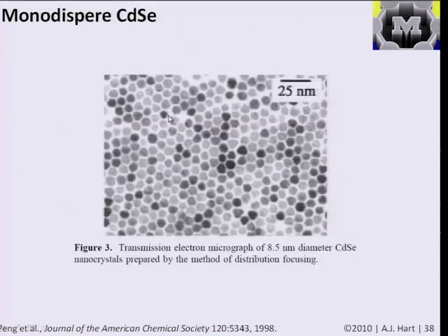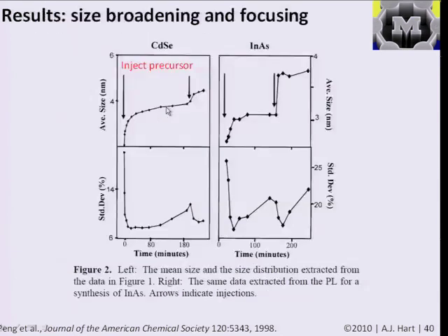And it turns out that what we saw in the TEM is in fact a fantastic result, a very highly monodisperse distribution of structures which gives those very pure optical properties. And ideally we might want to have them atomically precise, but getting down to the levels of standard deviation being a few percent of the diameter is a very good result that is enabled by understanding of these nucleation and growth dynamics. So that's where we will pick up next time.